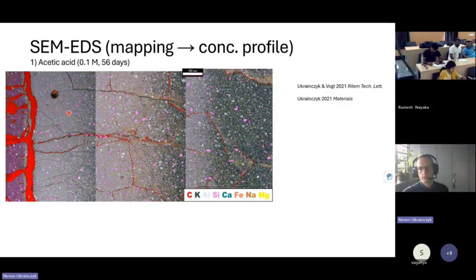And after polishing, you need to fine polish it with 1 micrometer, even less. You go in stages with polishing. It is described here also inside. And then you can put it under the microscope. We have the environmental microscope, so we don't have to do the coating. We can use it under low vacuum.